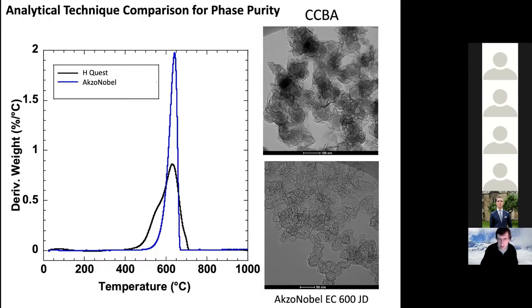The reason we're using AkzoNobel as the reference, although the contrast between these two TEM images, upper and lower, is a little bit different, and the magnifications as well, you can see that there's considerable internal structure within the particles of both carbon forms, namely the microwave produced carbon on the right, conductive, a high degree of internal structure, and ribbons external, versus that of the AkzoNobel. They are quite similar in that regard, as also manifested by the overlap between their derivative TGA spectra.